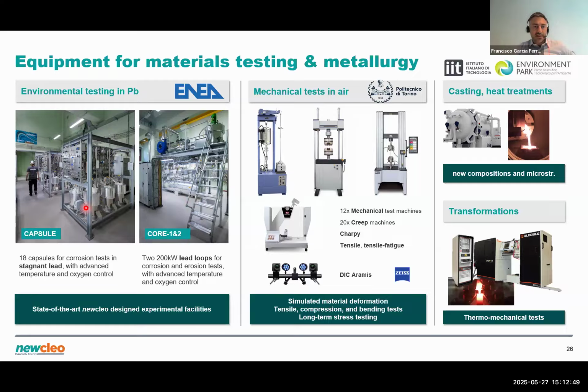So corrosion testing in stagnant capsules. We have 18 of these capsules, each one with roughly 1 liter of lead, which can handle temperatures up to 750 degrees with automated oxygen control systems. And similar for our core installation, we have 2 flowing lead loops. One can host 32 samples, the other one can host up to 160 samples. The first one will be used more for high turnover tests and European projects context, while the second one will be mostly utilized for running very long-term tests and generating statistics.